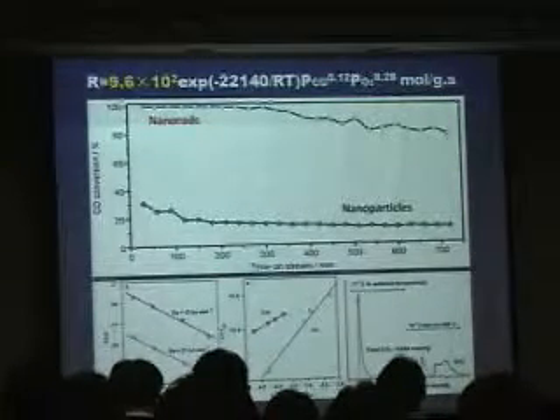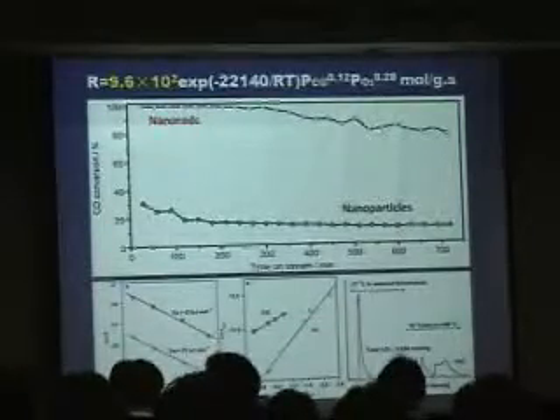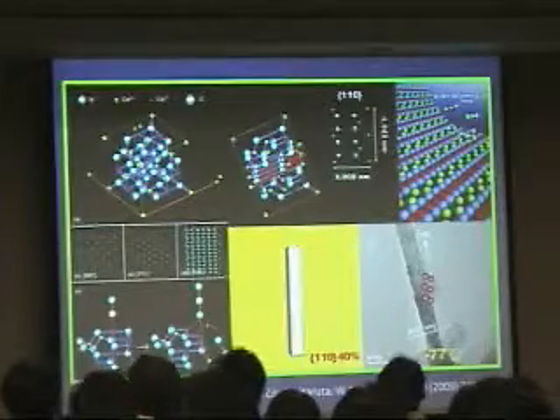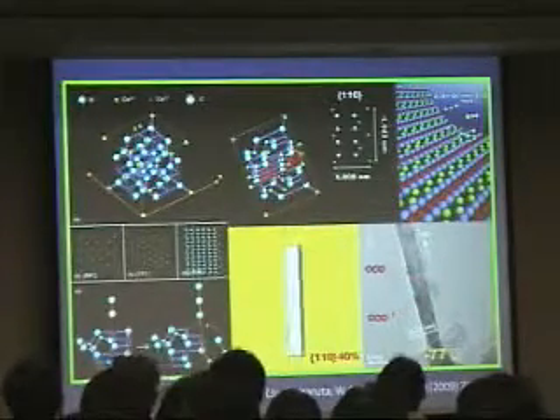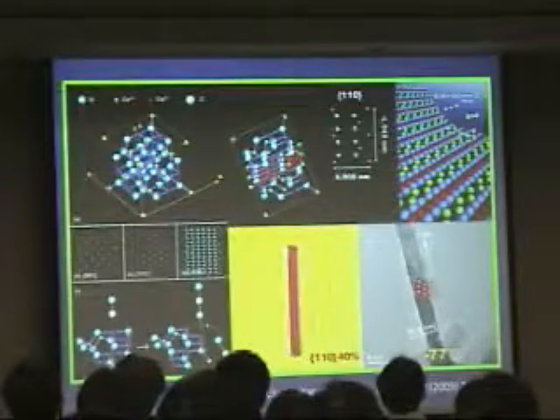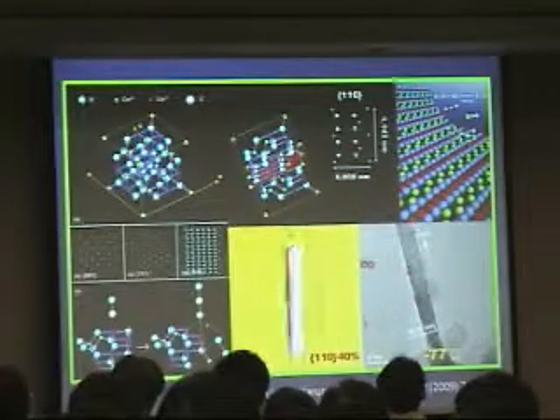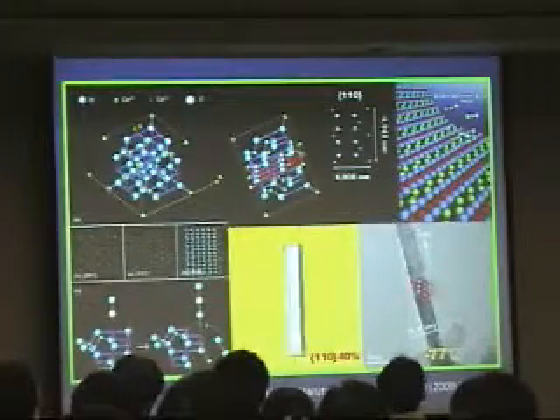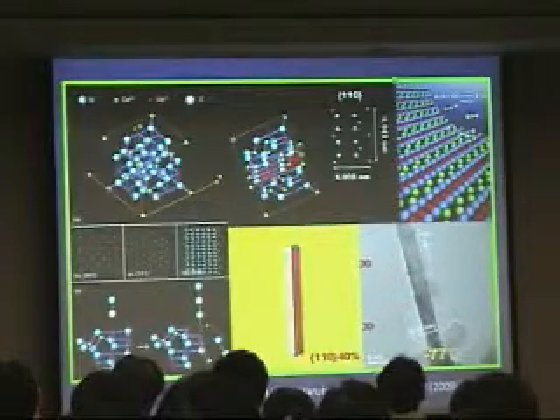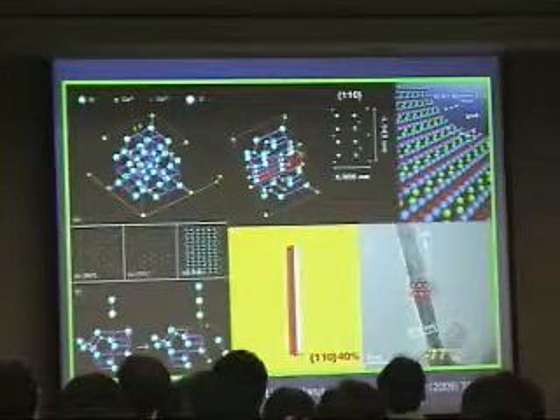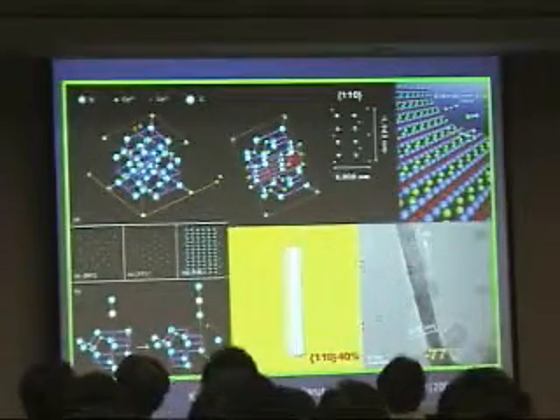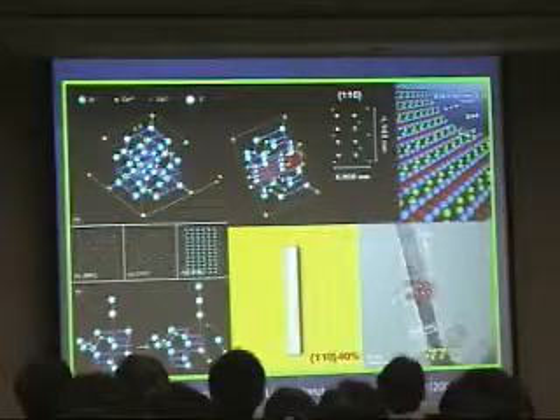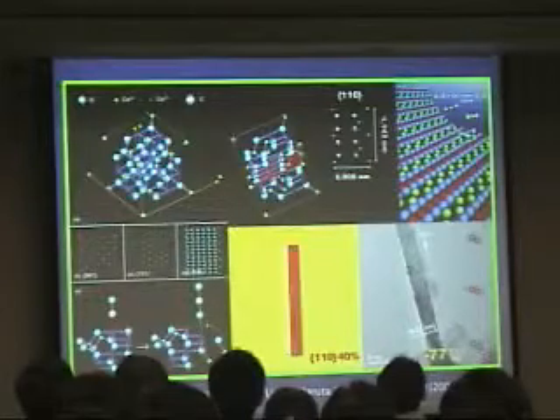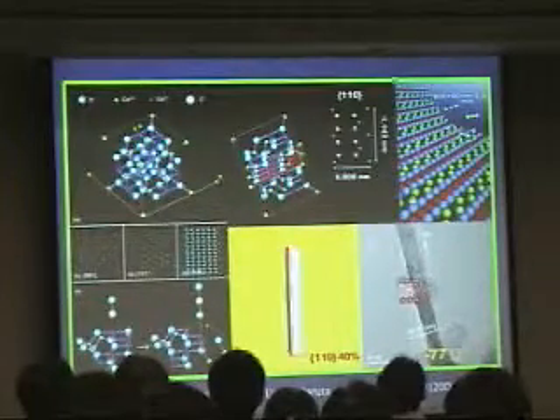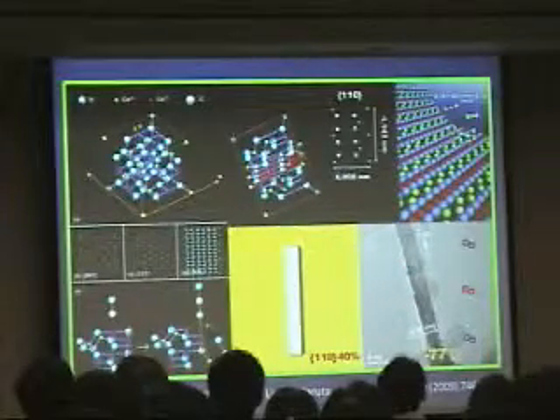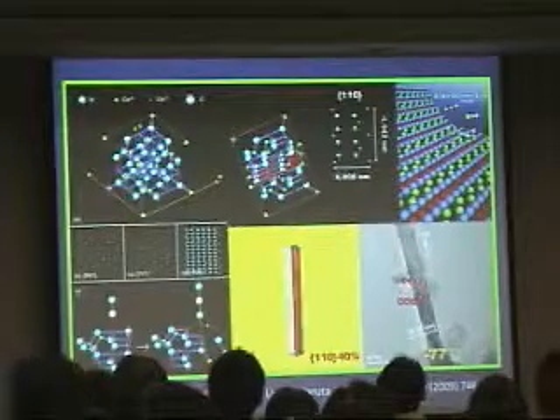And how does the active site number become so much larger on the nanorod surface? We find that for this nanorod, the narrow side contains the 110 surface. This surface is constructed by cobalt 2 plus and cobalt 3 plus. This is very important. Usually this surface cannot be exposed for normal spherical particles. But in the rod shape, they have space confinement or something like that. It exposes 40% of the 110 surface. So that means the cobalt 3 plus density is high on the surface of this nanorod. That's why it causes the higher activity than the typical spherical particles of cobalt oxide.